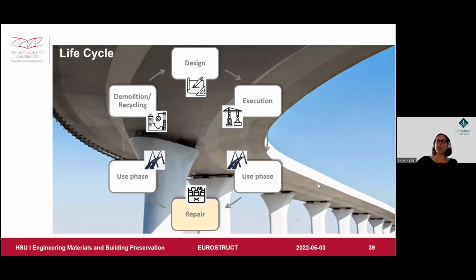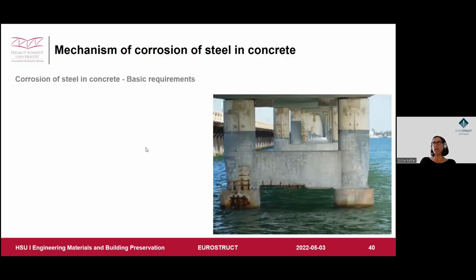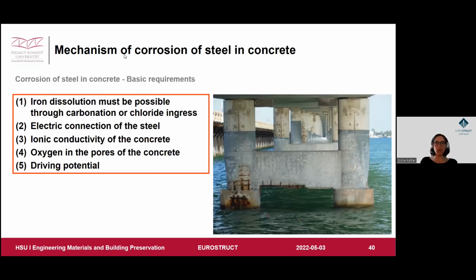And I would like to continue with the repair, but please keep in mind, I also have to look at the watch, and I would like to keep it short for the repair. Here, I want to come back to the basic requirements. Keep in mind, you have to exclude one of them just to prevent corrosion. The easiest is that you prevent the possibility of iron dissolution due to carbonation or chloride ingress. So you have to exclude the chloride, or you have to exclude the carbonated concrete, so you do a total replacement of your concrete. You can also apply cathodic protection systems, which exclude the driving potential. It also excludes the possibility of iron dissolution.